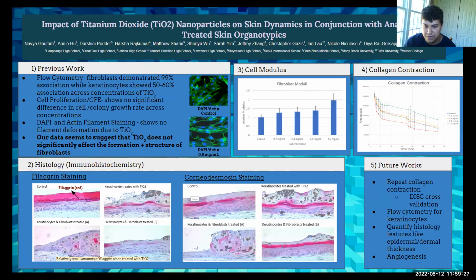In order to validate the results we saw in our initial analysis, we conducted numerous tests on both epidermal keratinocytes and dermal fibroblasts. Some of these tests were discussed in the previous symposium. These were flow cytometry, where we found about 50% association with titanium dioxide in keratinocytes and nearly 100% in fibroblasts, fibroblast cell proliferation and keratinocyte colony formation efficiency, which both showed that titanium dioxide made no significant impact on growth rate, and lastly, DAPI and actin filament staining, which showed no significant deformation of actin filaments.